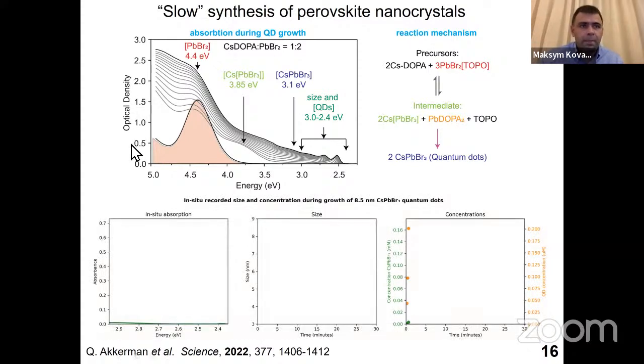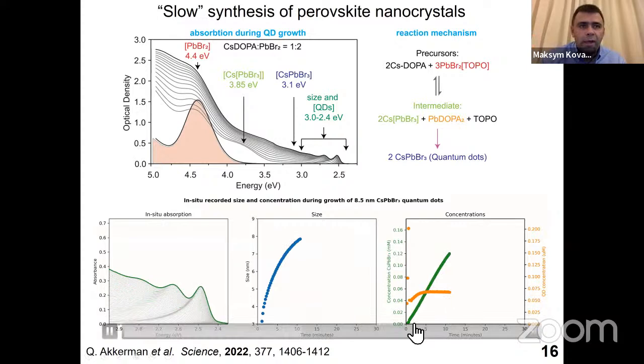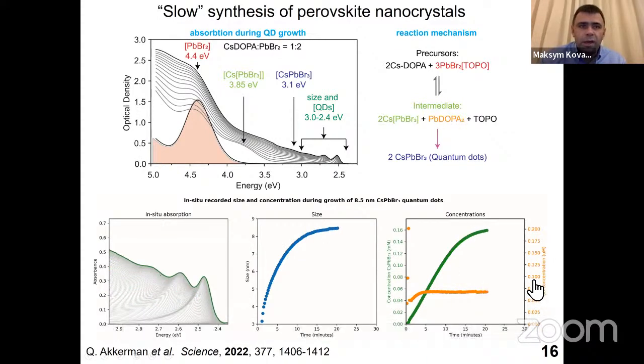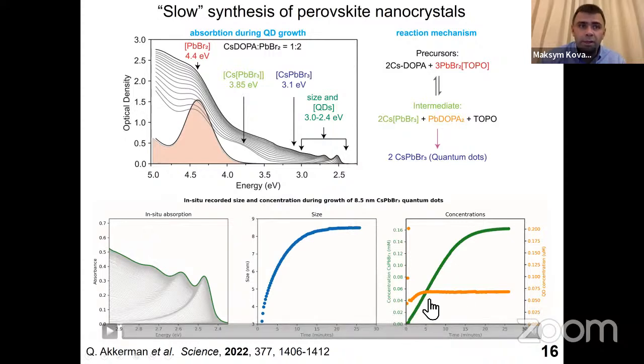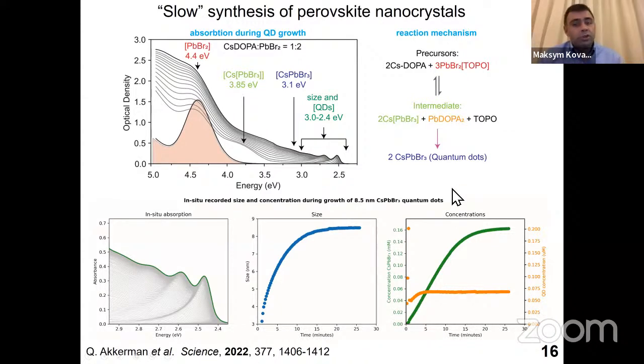And just to give you an idea, you can actually observe that your nanocrystal quantity, the concentration of quantum dots, will rise and then saturate. That means you have reached the plateau in your concentration and in your size. You know then that at this moment the whole reaction is finished, and then you can isolate your nanocrystals in a high yield. So just to give an idea, this synthesis is so much more convenient and better controlled that we now entirely shift to this approach.